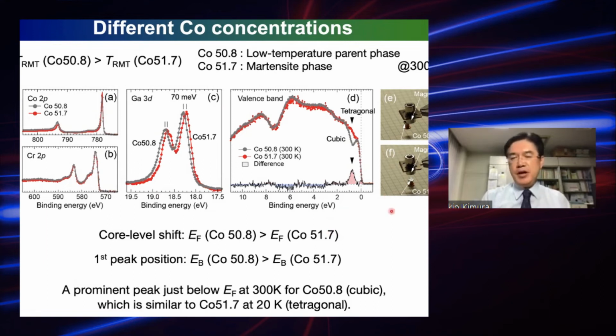By the way, we actually always check the state of magnetization of the sample by just attaching a permanent magnet. As you can see, the cobalt-poor sample is magnetized, I mean, it attaches to the permanent magnet, because it is ferromagnetic. While the cobalt-rich sample does not attach to the magnet, which means it is already in the martensitic phase at room temperature. So as you can see, the density of states is much different in terms of the appearance of the peak and the appearance of the dip in the cubic phase. This cobalt-poor sample is in the cubic phase.